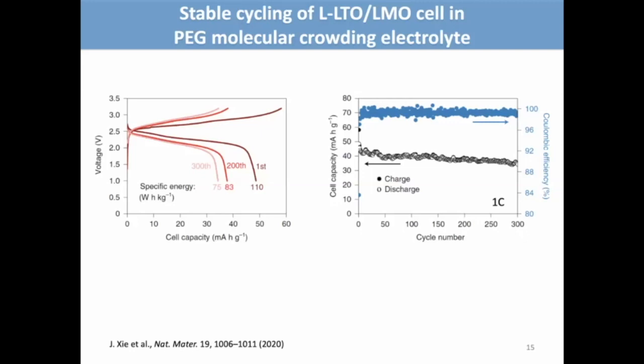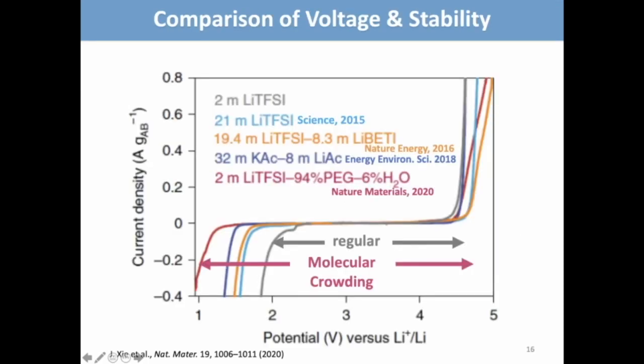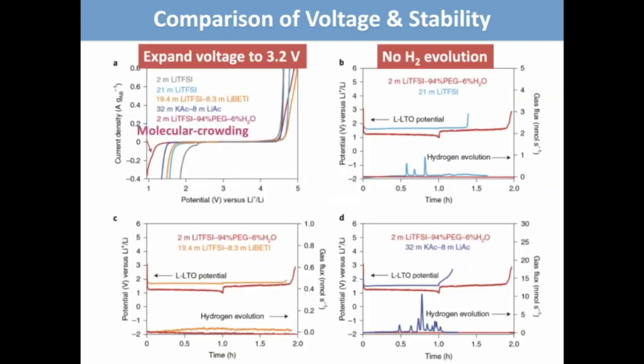So with this electrolyte, we're able to cycle this full cell about 300 cycles with about 80% capacity retention at 1C rate. So we also want to compare the water stability window of our electrolyte with other types of highly concentrated electrolytes. And we do that with identical electrodes just for the parallel comparison. So you can see the molecular crowding electrolyte, in fact, provides a wider stability window compared to the highly concentrated electrolyte, to further support its efficacy for stabilizing water.